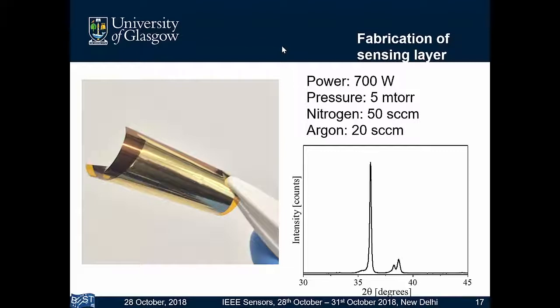After deposition, one way to know whether it has really grown in the 002 orientation is to do an XRD. If we see a peak at 36.1 degrees, the higher the peak, the better the piezoelectric material is. So we see a significantly high peak here on polyimide. So it did have piezoelectric properties.